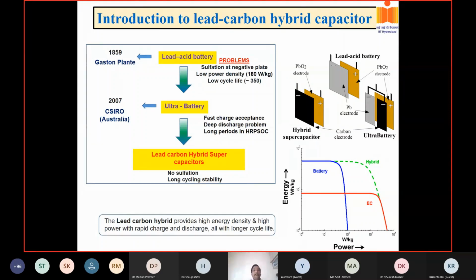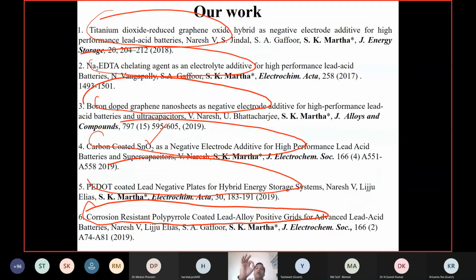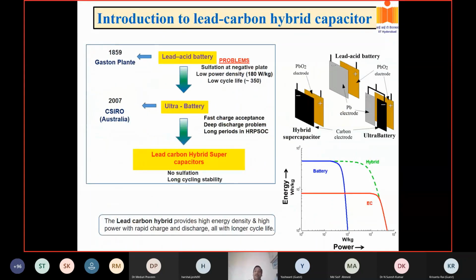So what I was telling, additives to the active mass improve the performance. I didn't change the electrode configuration. I use the same negative electrode of the lead acid battery as such and added some additives. If you see all these papers, less than 1% additive, even 0.1%, 0.25% of additive has been added to this electrode to improve the performance. But still, the sulfate issue is not 100% removed.